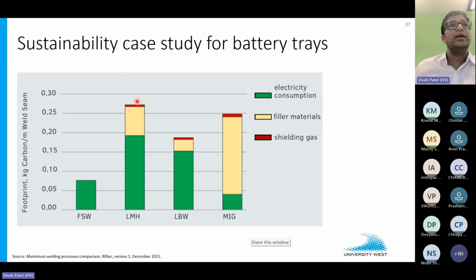we tried to quantify the carbon footprint. So how much carbon is emitted during the process, you can see this comparison of electricity consumption and amount of filler materials used. In friction stir welding, there is no filler metal, no shielding gas, and also electricity consumption is quite less here. So overall, the carbon footprint was found to be very, very less compared to the rest of the welding processes in terms of welding speed and tensile joint strength performance.